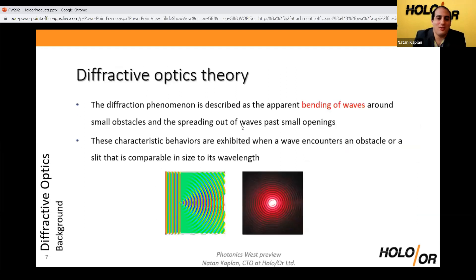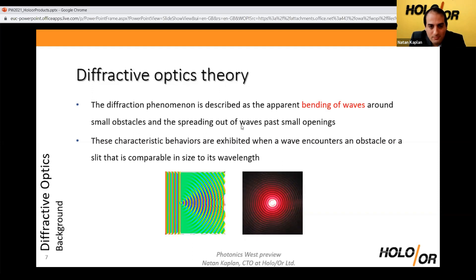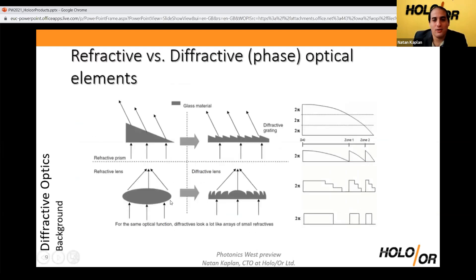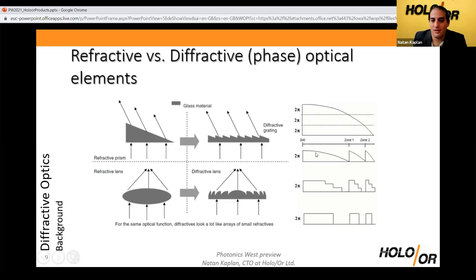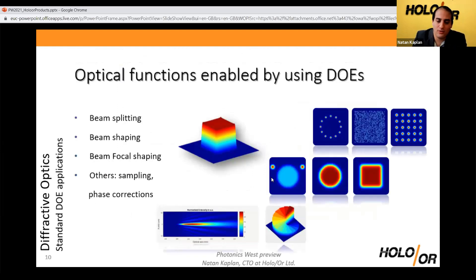What does this wavefront do? It creates diffraction. For the right height of these etched patterns, the laser waves going through the structure are diffracted and delayed by a certain controlled delay. This can create effects such as a lens called a Fresnel zone plate, or a blazed grating — the equivalent of a refractive prism. All of this is done at a layer that is usually the height of one wavelength — micron or less — making the elements very robust to damage at high laser damage thresholds, essentially the same as a flat window of the same material.